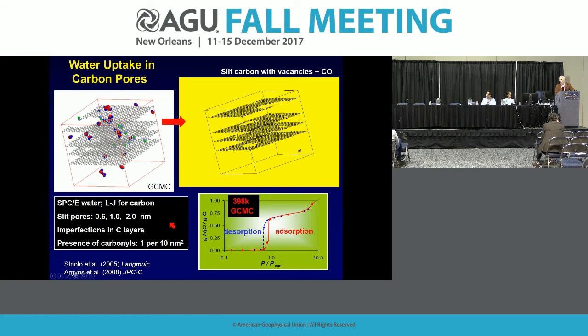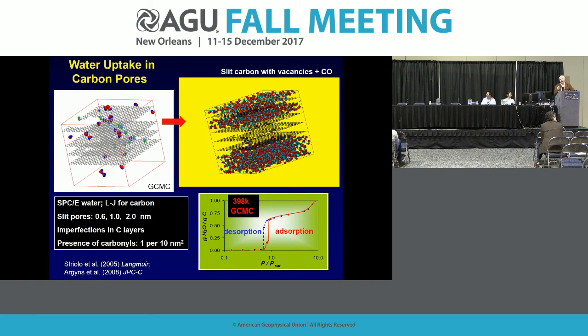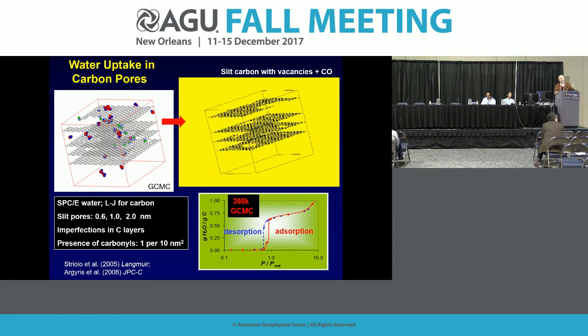So we go ahead and click this. The first thing you're going to see is the larger slit pores start to fill fairly early on, and then the narrower pores. And as it dewaters, you're going to see the opposite. You're going to see the thick water in the thicker pores hold on to itself, and they'll dewater last. And so we actually were able to emulate that adsorption curve very well, which you see in the lower right. It's just one example of several that we've done like this.